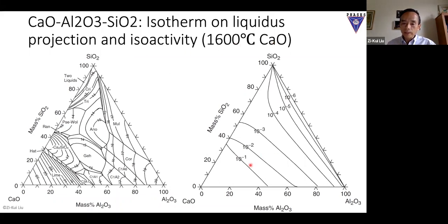If the calcia is 0.1, so that's the line here, okay? In order to keep calcia activity at 0.1, you have to balance the alumina and the silica on this line. And also it's very important to see, right, this is like 70% calcia, but activity is only 0.1. So the activity of calcia is way off compared to its composition or mole fraction, right? That's why you have very, very strong interaction in the system. So that's important for the processing control.